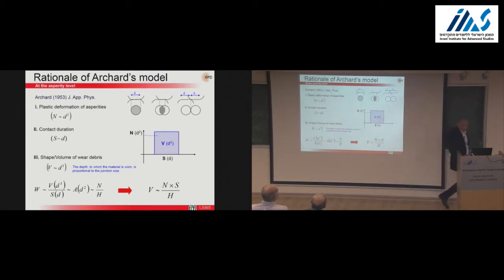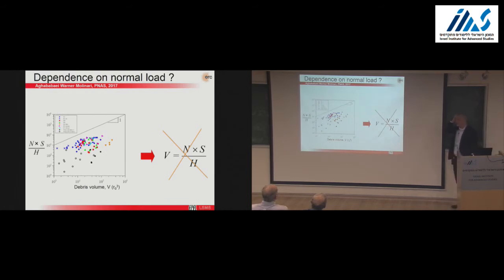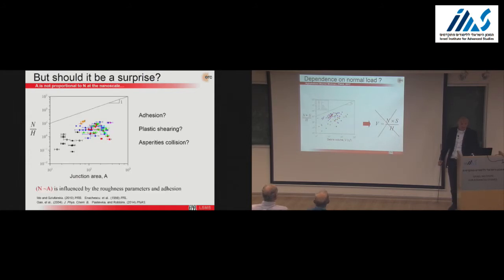Okay? So this is something we can do. We can measure this. What we control is those parameters. We control H, we control N, and we can measure the debris volume. And we do not find this proportionality from our data. And what you have here compiled is a 2D, 3D diamond type materials calculation. So we do not see this proportionality.